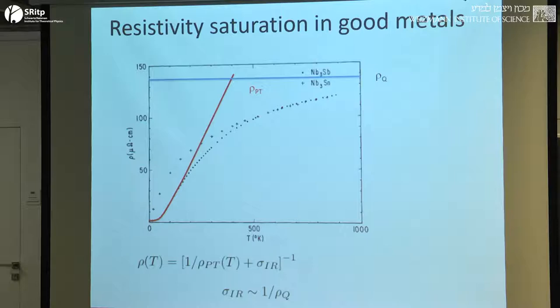So if you just take the Bloch-Grüneisen expression for the resistivity for these, fit to the low temperature data here, you get this red curve, and what you see is the red curve fits very nicely until the resistance starts to get comparable to the quantum of resistance where you would expect the quasiparticle picture to break down. And in keeping with your expectation, something indeed goes wrong. And the something that goes wrong was described as resistivity saturation.